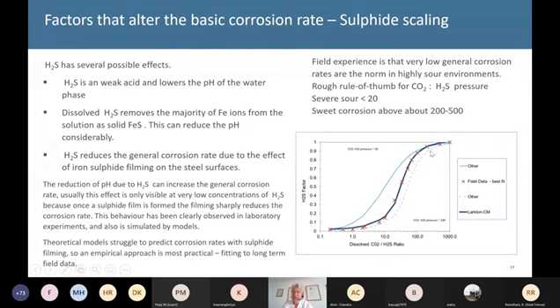The blue line is the Larkton software model that we've fitted to this data that we have. There are two other models that we're aware of out there, and one of them is tending to give, we think, overconfident reduction. We think that the corrosion rates are actually a little higher than this is giving, and another model is rather too conservative and is not really taking proper benefit of what we see, and we do a lot of work with sour service, so we have confidence in this. Try to remember these facts about the pH, because I'll come back to that in a moment. I don't want to spend long on this.